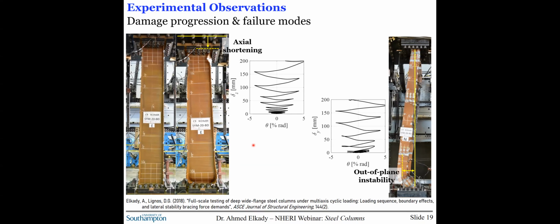As you probably observed in the videos, the primary failure mode is local buckling, the progression of which resulted in appreciable column axial shortening, reaching around 50 millimeter or about 2 inches at 3% drift. What's more interesting is that at drifts larger than 2%, local buckling at the base plastic hinge was coupled with out-of-plane instabilities in the form of out-of-plane deformations and twisting of the member.